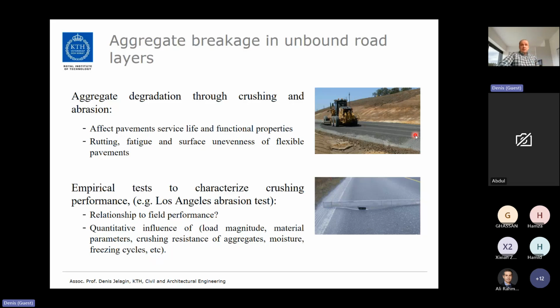And the way we deal with this problem practically right now is through empirical performance tests, such as the Los Angeles abrasion test. But there are a lot of different variants of those ball mill type tests. And those tests do allow us to screen materials with guaranteed inferior performance. But at the same time, there is a big discussion about the relationship of those tests to field performance, and it's not necessarily very strong.